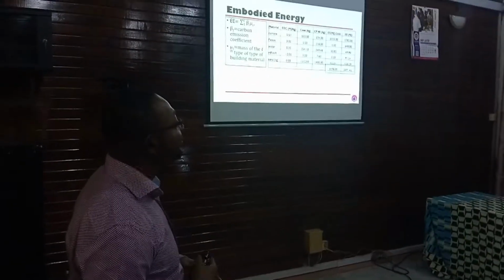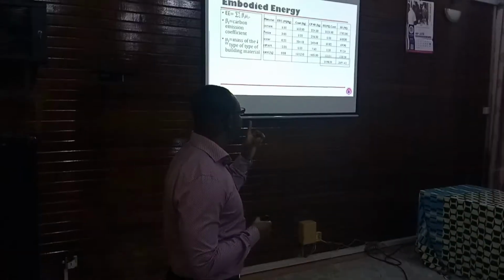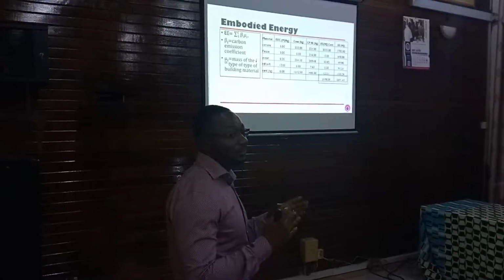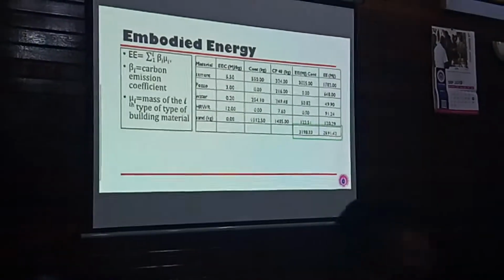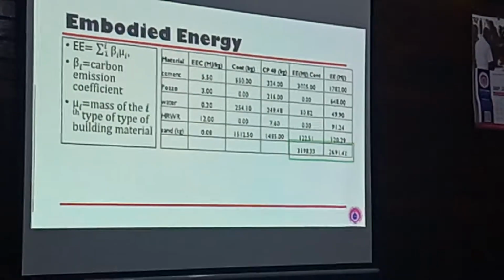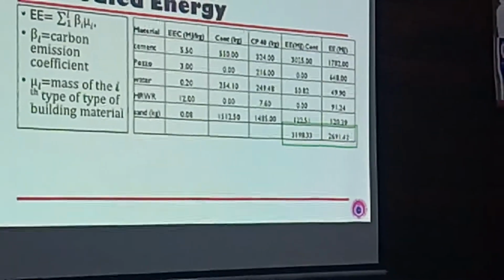So if I do the calculation based on this embodied energy and the masses of the material, now the masses of the material is per meter cube. So this is what I'm achieving. The embodied energy for the control, that is the mortar mix without the pozzolan, was giving me 3,198.33 megajoules. And the embodied energy of the one that I used 40% to replace is giving me 2,691.43 megajoules. But don't forget, I have stated that embodied energy has a direct relation with carbon dioxide emission.